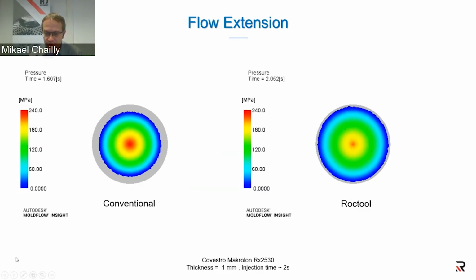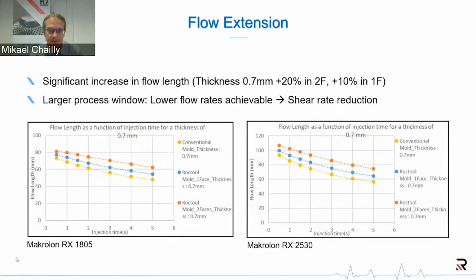Just to give you a brief insight, if we go to the next slide - on this slide we have the first configuration, which is with a disc of 0.7 millimeter, and we have the graphs obtained for the two materials. Of course, with such a thin material, we couldn't fill the full flow length of 150 millimeters, whatever the configuration, because we are reaching this pressure limit. But considering the maximum pressure limit I mentioned earlier, we can see that in Roctool conditions, whatever your injection time is, hitting both sides, we managed to increase the flow length for both materials.